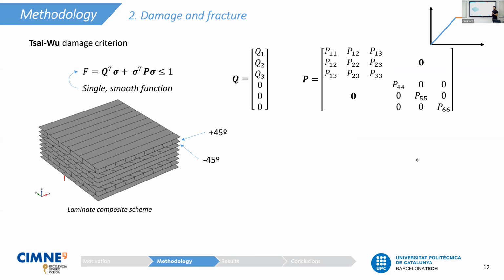Once the mesh has been generated and the material has been characterized, we enter the second part of the methodology, which is called damage and fracture. In order to model when the component is damaging, or to establish a threshold in which we go from the linear regime to the non-linear regime, we have to define a damage criterion. Several damage criteria exist, such as the typical von Mises criterion, and so on. But for plastic materials that have orthotropic properties and that have different strengths in tension and compression, the typically used damage criterion is the Tsai-Wu criterion.